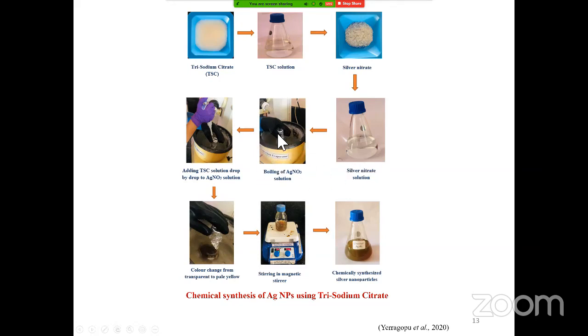100 ml of silver nitrate solution has been brought to boiling point, and after that 12.5 ml of trisodium citrate solution is added, and after that the color changes from transparent to pale yellow, which indicates the formation of silver nanoparticles. And proper stirring for about 30 minutes gives uniform size nanoparticles. So we get chemically synthesized silver nanoparticles.